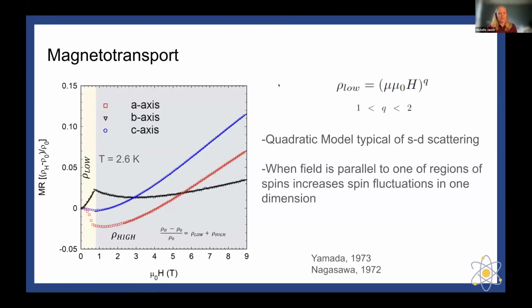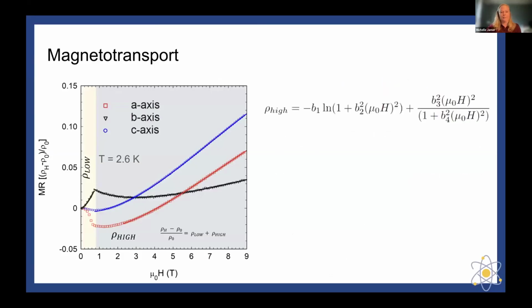And whenever we see that the field is parallel to one of the axes, it increases the spin fluctuations in one dimension, but also decreases the spin fluctuation in a dimension that's perpendicular to it. So whenever we are looking at this type of scattering, what we notice is that we do see this huge increase in the C-axis, but the A-axis is somewhat suppressed, which is standard to this model for SD-type scattering. This is also known as the Rivier's lattice model that you can look into if you're interested in looking at the different types of transport.